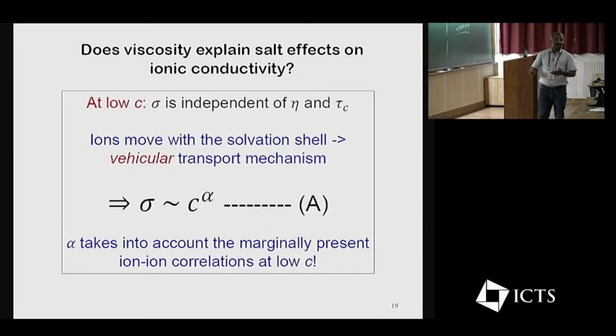So what happens at low concentration? The conductivity in an electrolyte at low concentration is simply determined by the number of, that means the concentration of, ionic species. In the literature, as I showed, it was typically assumed that it's proportional to C, but we are introducing here an exponent to account for the marginal, but present, ion-ion correlations at low concentration.